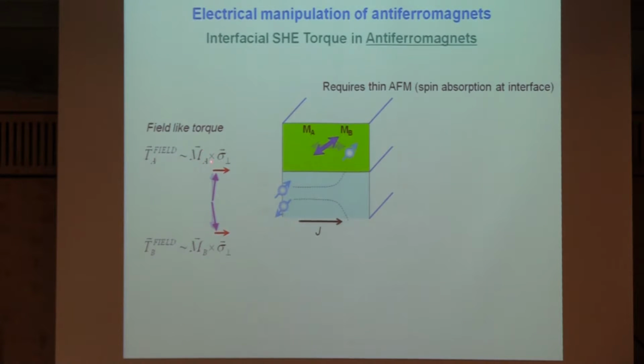But on the other hand, you have a certain spin lifetime, and if the spin lifetime is much shorter than this precession time, your steady state solution of this problem is that you actually have only a spin accumulation which has the same polarization than the one you generate via this spin Hall effect in this geometry.